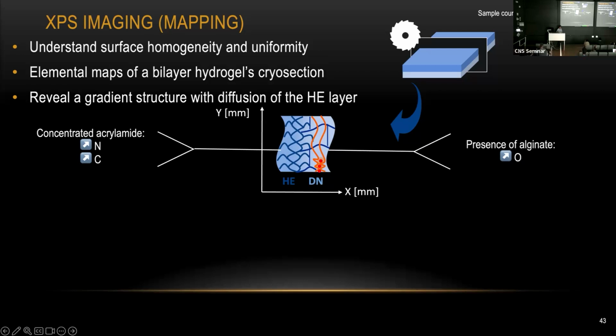And the student tried to combine these two, put these 2 pieces of hydrogel together. And what she's hoping to see is the nitrogen slowly diffusing into the alginate layer here. But she can't see anything, so she needs some data to prove it. So we go ahead and do some mapping using XPS. She put these 2 pieces of hydrogel together on top of each other, and we try to do the measurement on the cross section here.